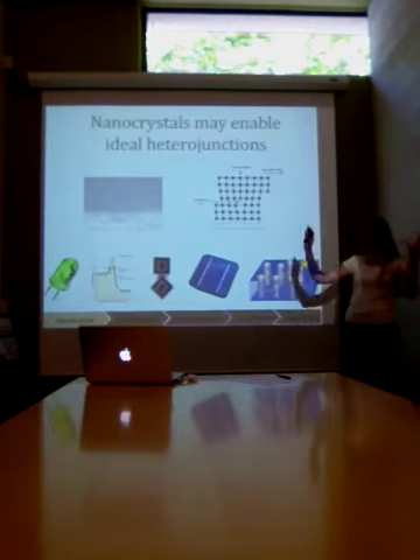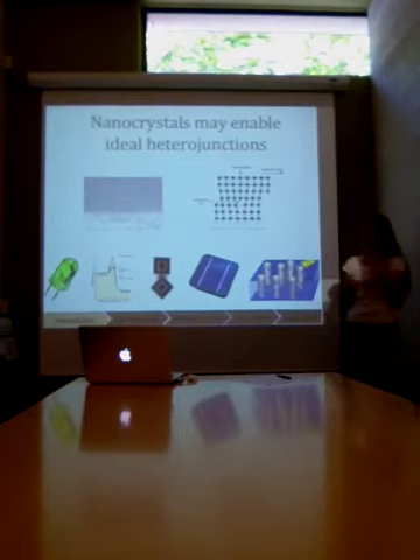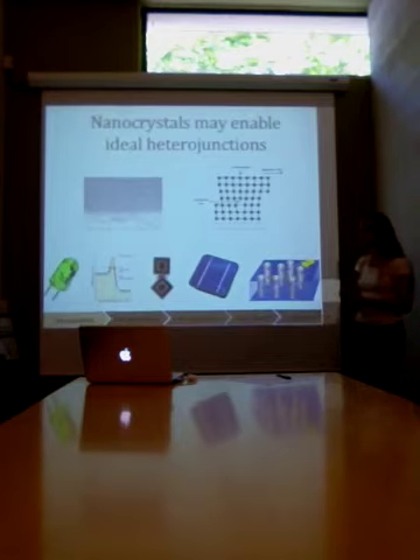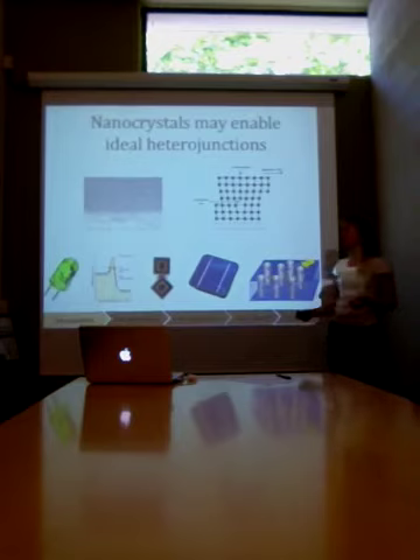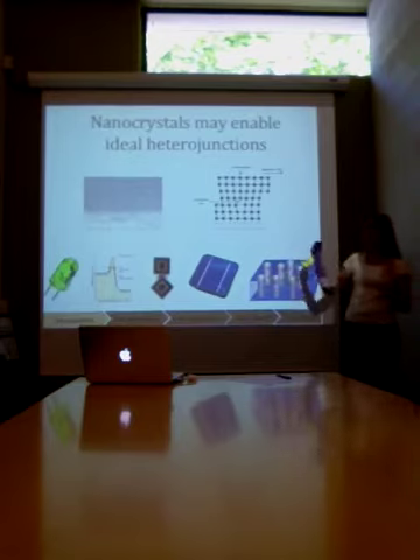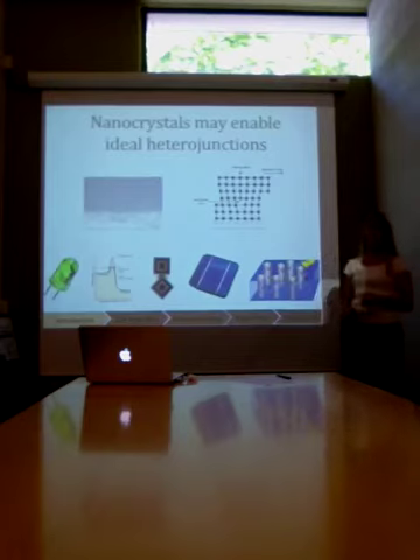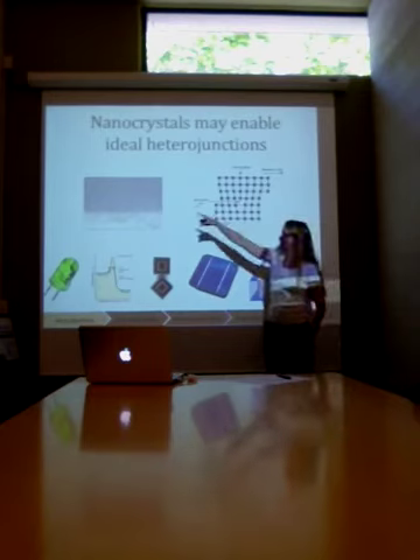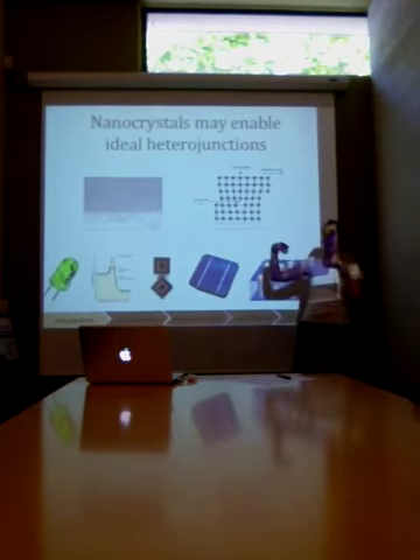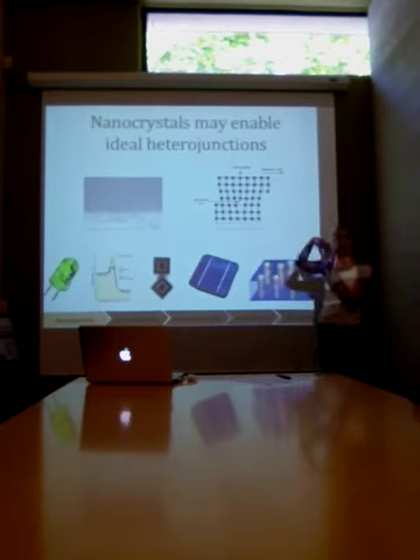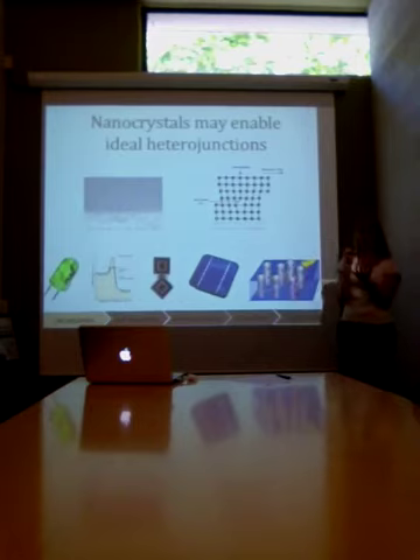And when you engineer that to have the right band alignments between all of these materials, you can manipulate the flow of the electrons in your system. So heterojunctions are useful in things such as light-emitting diodes, catalysis, sensing, photovoltaics, and water splitting. In this transmission electron microscope image, you can see an epitaxial heterojunction where two lattices are coming together. And the lattice is simply the atomic spacing in the crystal.